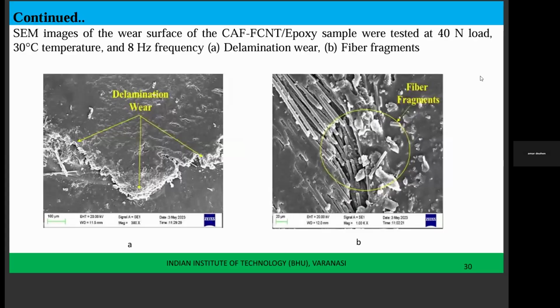For the wear surface of the coated aramid fiber and functionalized CNT with the epoxy, at 40 newton load, 30 degrees centigrade temperature and 8 Hz frequency, you can see delamination wear as well as wear fiber fragments on the surface under the microscope. Small fiber fragments are observed, and breakage and delamination is taking place at that particular length scale. Next slide, please.